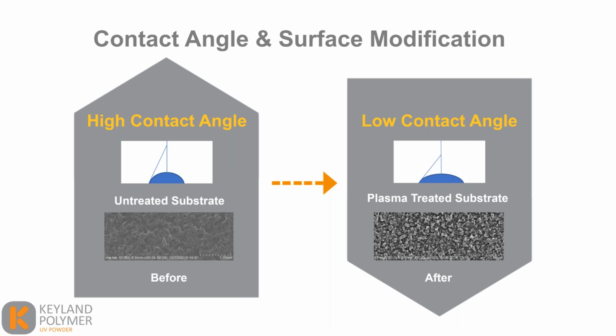So on the left, it's a high contact angle, has low wettability and low surface energy, which indicates it's a hydrophobic surface. On the right, it has a low contact angle, and this is after plasma, high wettability, high surface energy, which typically indicates a hydrophilic surface. And at the end of the day, it's good wettability that allows for maximum bonding strength between two materials.